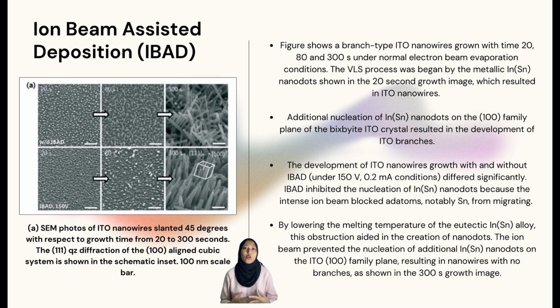IBAD inhibited the nucleation of In-Sn nanodots because the intense ion beam blocked adatoms, notably Sn, from migrating. By lowering the melting temperature of the alloy, this obstruction aided in the creation of nanodots. The ion beam prevented the nucleation of additional alloy nanodots on the ITO 100 family plane, resulting in nanowires with no branches, as shown in the 300-second growth image.